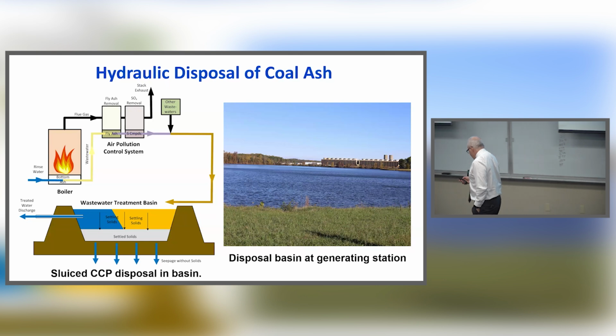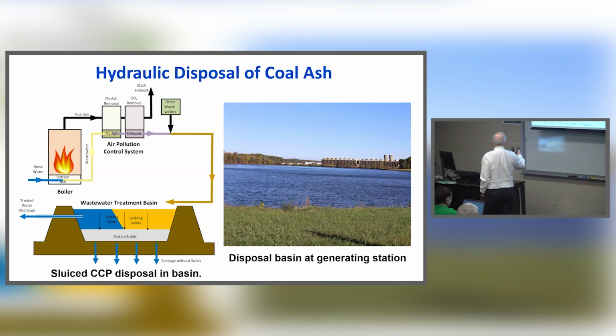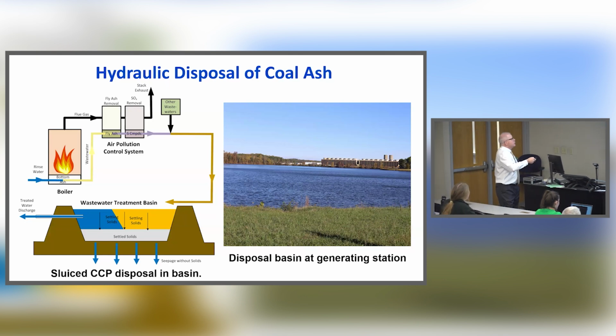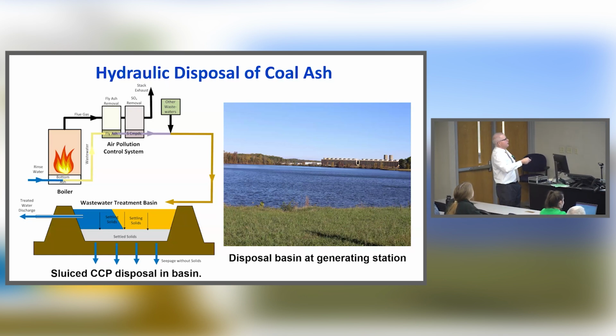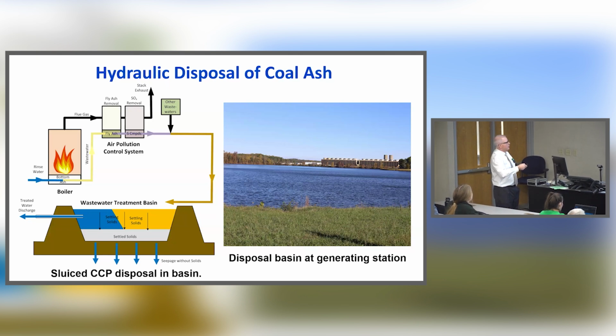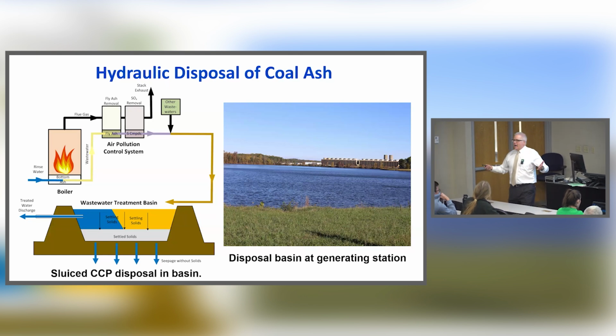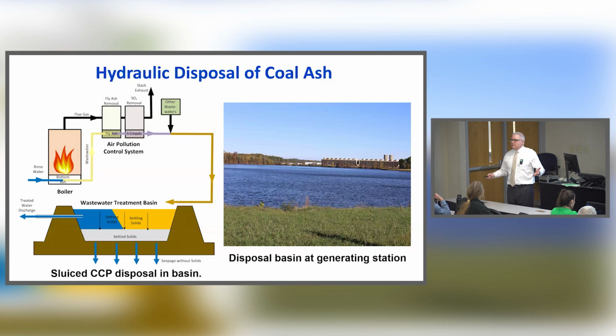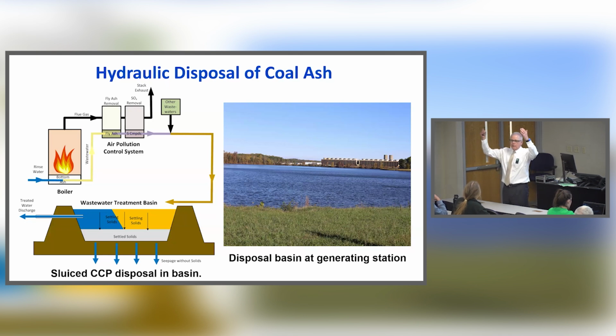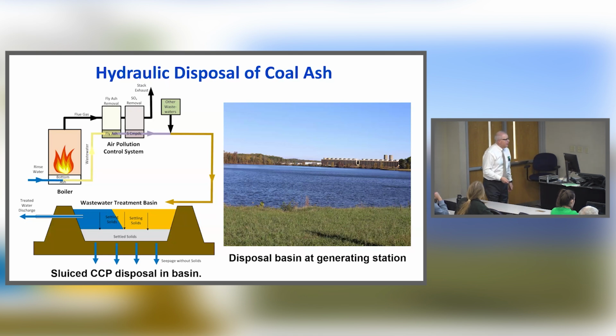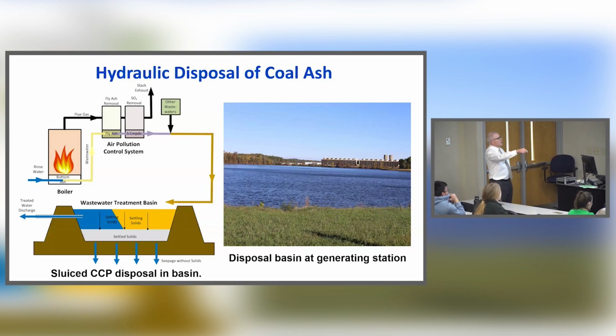So you think of, we have a boiler, we're burning the coal, we're generating flue gas, and we're removing the fine particulate from that with a system. We have bottom ash that's being generated at the bottom of our boiler, and we convey that ash with hydraulic techniques. So we just essentially rinse it out with water, put it in a pipeline, and pump it out to a pond. I think of it kind of like hosing off your garage floor, the particulate off your garage floor. It's not a lot different. You essentially fluidize the particulate, put it in a pipeline, and send it out to a wastewater treatment basin.